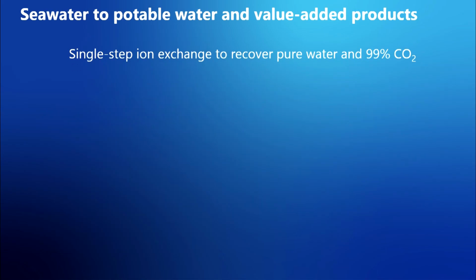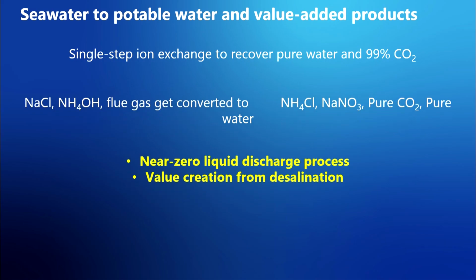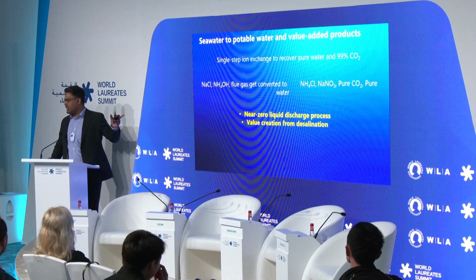Then the bicarbonate liquid we generate can, using some ion exchange process, give us back all the carbon dioxide and water. So bicarbonate becomes CO2 and water. If you think about the whole process, we start with sodium chloride and ammonium hydroxide in the feed, and flue gas which is a few percent CO2, and that generates ammonium chloride and sodium nitrate. Again, nitrate is coming from an ion exchange process, and pure CO2 again comes from the ion exchange process, and water. So there is no waste generated in such a process.